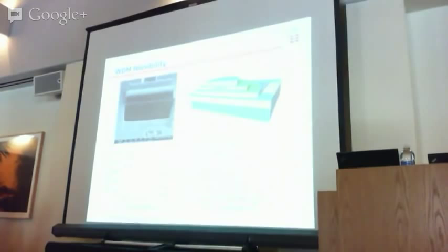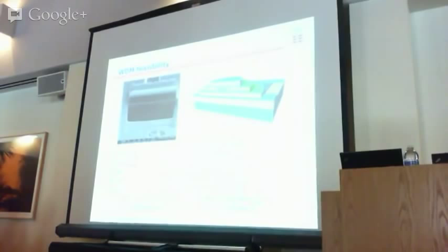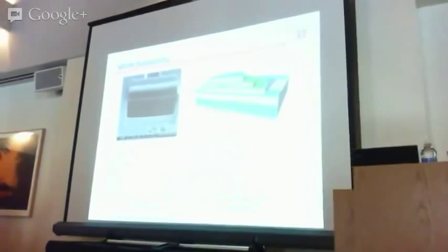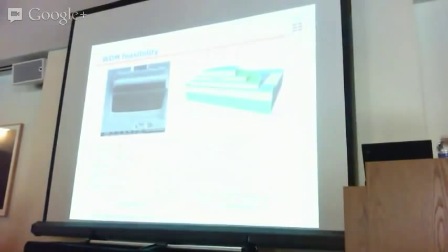And this is our fabricated sample, and this is a cross-sectional image of the fabricated sample. So we can see that we have the DBR here, the active region, and the silicon grating. When we measure micro-photoluminescence, the linewidth is quite narrow. Actually, it is limited by the resolution of the spectrometer. So the Q factor is comparable to the conventional VCSEL structure. And when we vary this grating parameter, from the same epi, just by changing the grating patterning, we could achieve a different wavelength. So this functionality is also quite adequate for WDM capability.